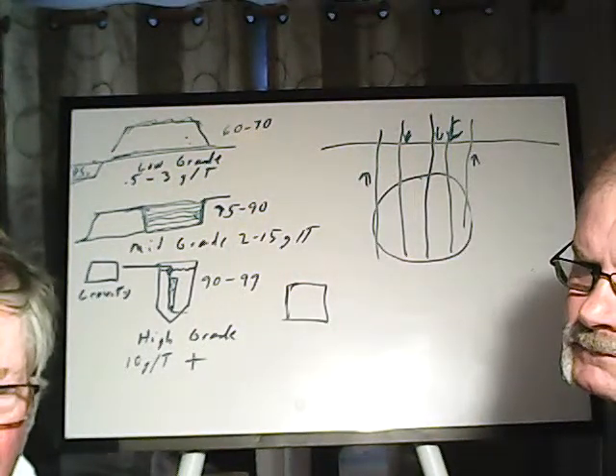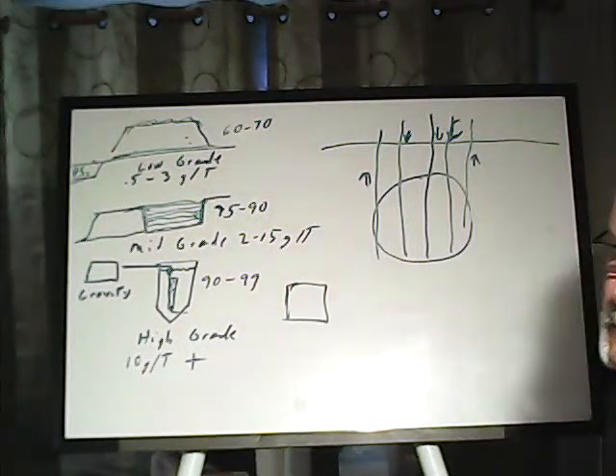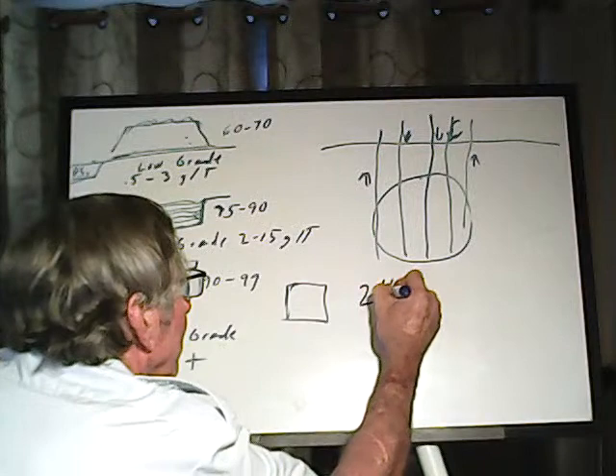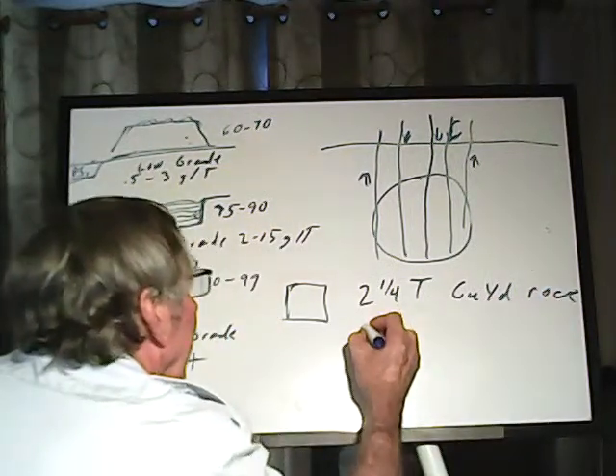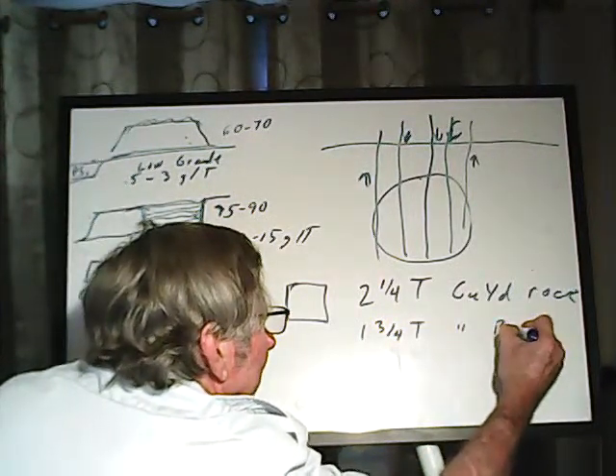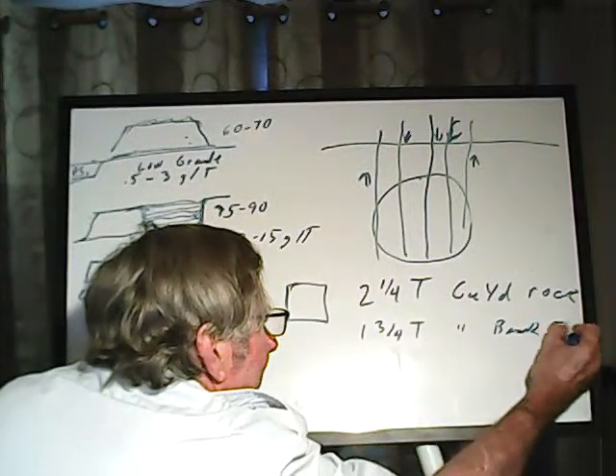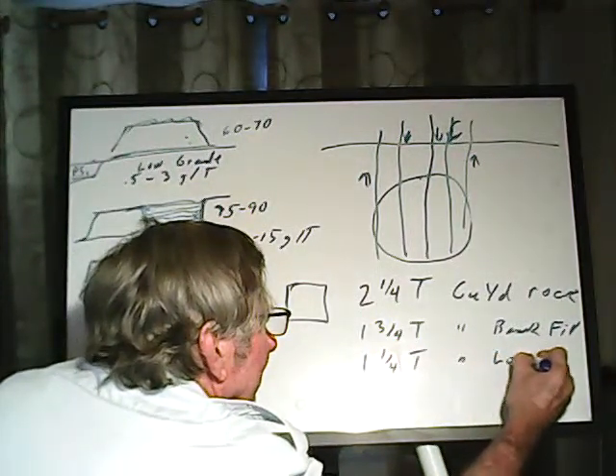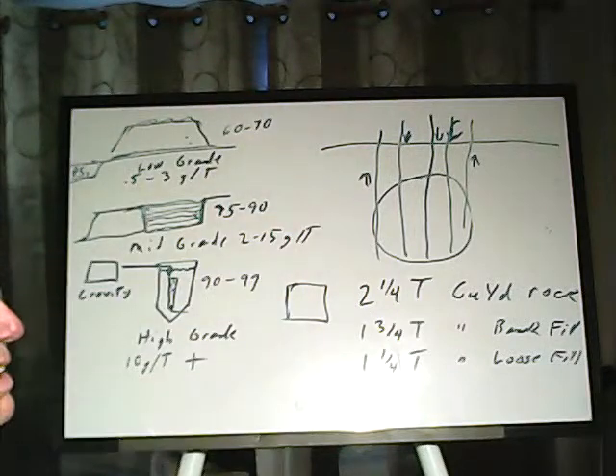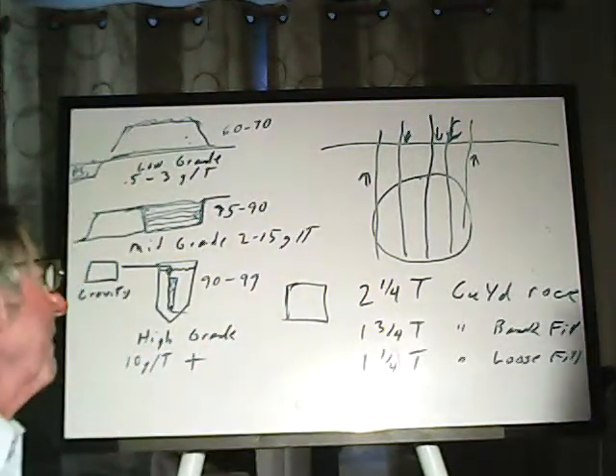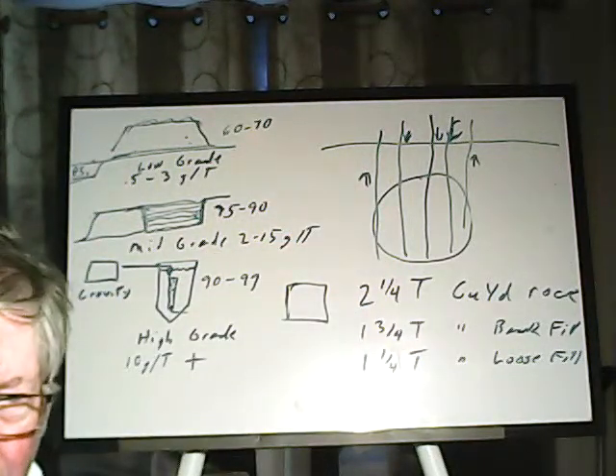How many yards to a ton? If you are talking rock in place, you're talking about 2 1/4 tons per cubic yard. And about 1 3/4 tons per cubic yard for what they call bank fill, in other words dirt in place. And then about 1 1/4 tons per cubic yard loose fill, once you've picked it up and set it down again, it fluffs up quite a bit. Now those are just rough numbers. It varies depending upon the density of the rock, the kind of rock, particle sizes, all kinds of stuff. But those are good rough numbers to start with.